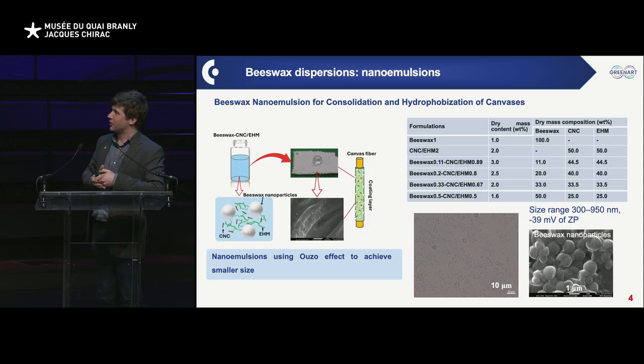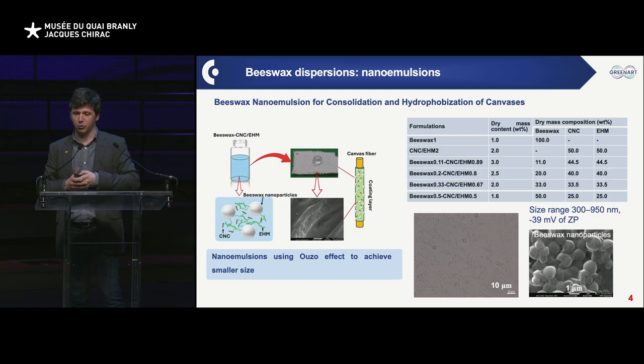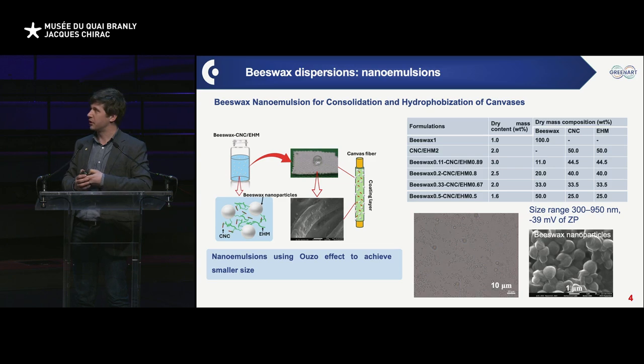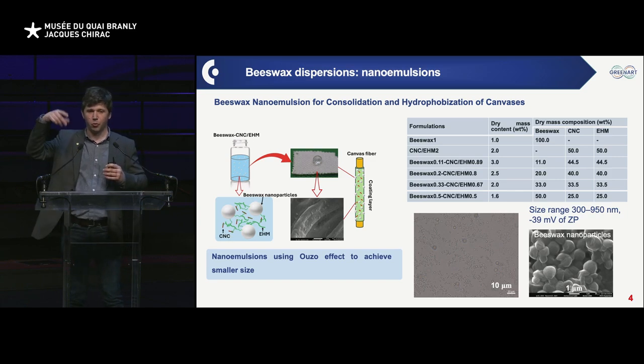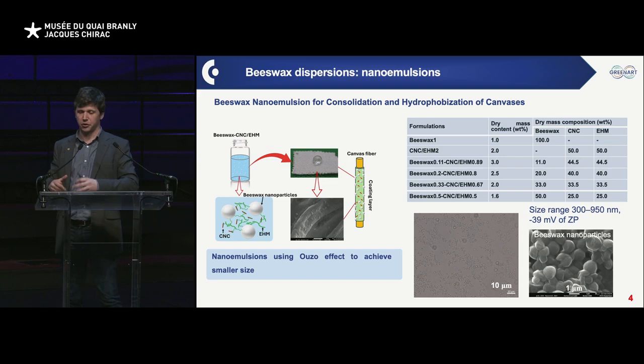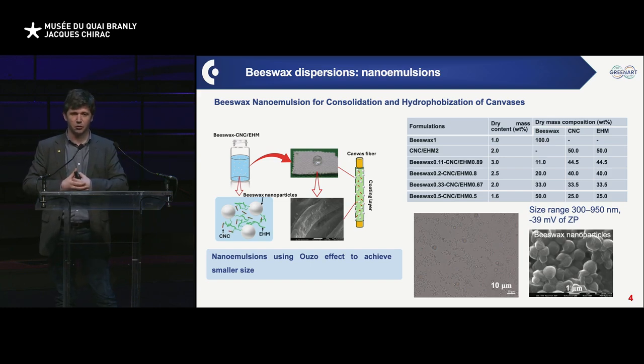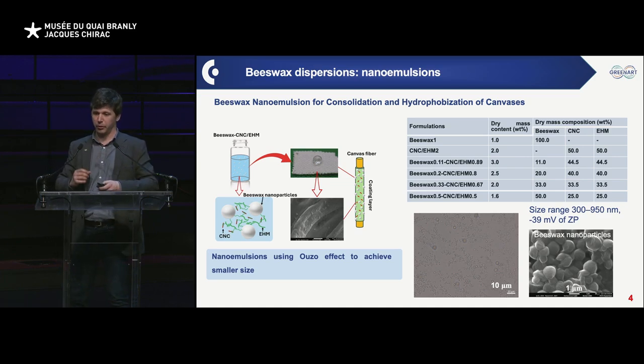The Ouzo effect is a natural self-emulsifying effect to achieve smaller size, and that is usually working really well. So basically what you do is that you take the beeswax, you dissolve it in a solvent that has a certain miscibility with water, and then you will dropwise add it to water. And then you will form small droplets, much smaller, because it's a self-emulsifying system. The solvent that is miscible in water will diffuse in water, and only the beeswax will remain. And well, we thought, okay, that could be interesting.